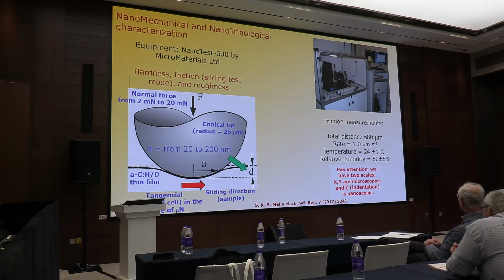After that, pay attention, because this is a nanomechanical system, a nanotribometer, but nano is only in the Z scale, because the X and Y are in the micro scale. The area of contact is maybe micrometers squared, but the scale of the indentation is nano. It's between 20 and 200 nanometers of indentation. In our experiment, we use 20 nanometers of indentation and then slide the diamond tip on the sample with different contents of hydrogen and deuterium.